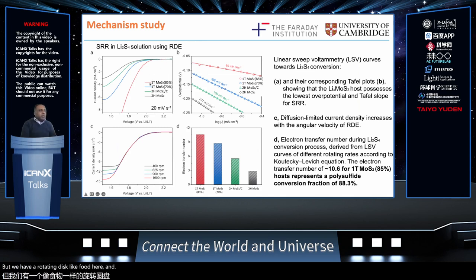And what we find is that, again, the catalytic activity of the 1T MoS2 for sulfur reduction reaction in this polysulfide solution, which is responsible for most of the capacity in lithium sulfur, the overpotential is the lowest, the Tafel slope is the lowest, suggesting that yes, the 1T MoS2 phase is active for the sulfur reduction reaction, and the kinetics are quite good. We can also then check whether the current is diffusion limited by changing the rotation speeds of the RDE electrode, and see indeed that that's the case.